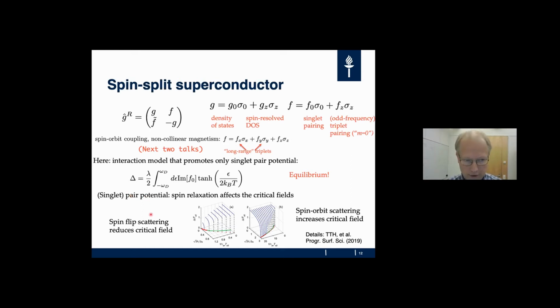More or less what you can find is that if you have spin flip scattering, this reduces the critical field for suppressing superconductivity, whereas spin orbit scattering increases the critical field. This might be the relevant phenomenon for heavy metal superconductors, where the critical field for the paramagnetic transition is much increased.